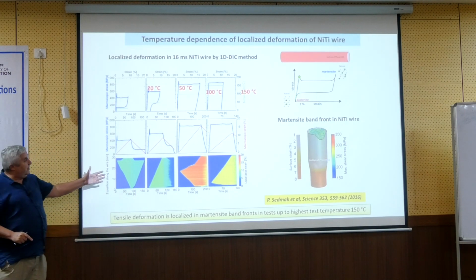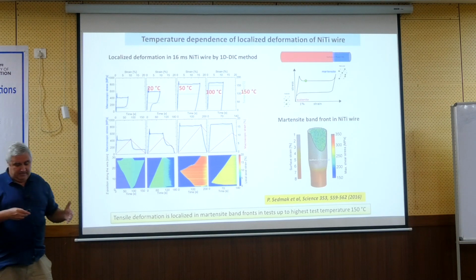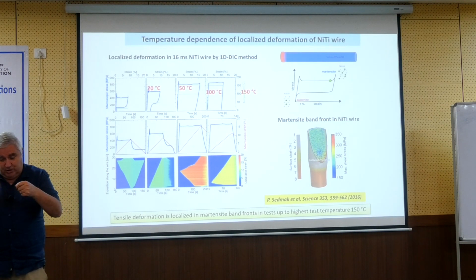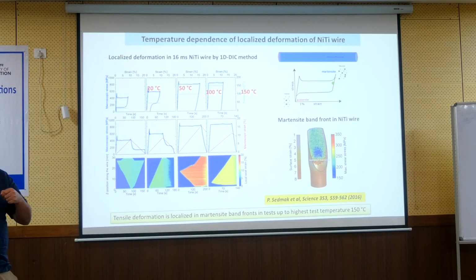In this way we can find out whether the deformation of the wire is homogeneous or localized. And you have this problem every time with nitinol wire, so be careful about that, and the evidence is this plateau. If there is a plateau, there is always localized deformation. And the question is, what is this plateau length? The plateau length here, in strain, is 7%, 10%, 15%, and 10%. So why is it so different?